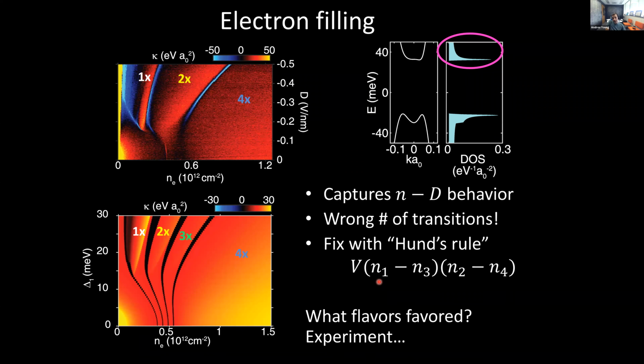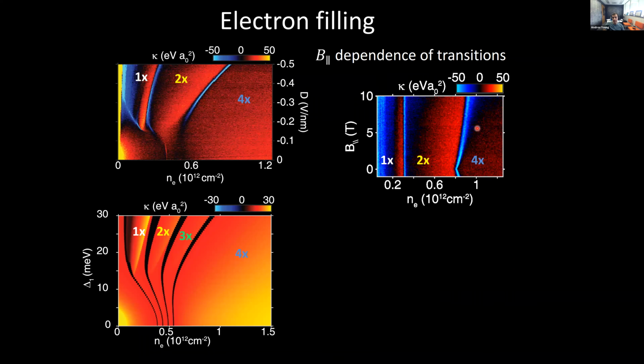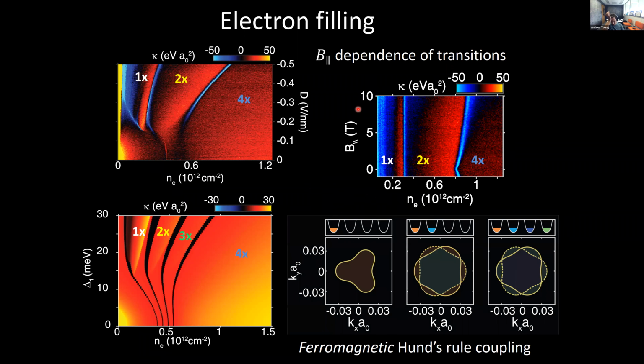And experimentally, you can actually work out what that Hund's coupling is using the in-plane magnetic field dependence. Without getting into the details too much, basically what we can find is that this 1-fold phase is fully spin and valley polarized. The 2-fold phase is actually spin polarized, but valley unpolarized.